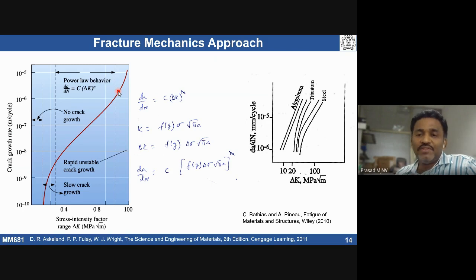People have established that a smooth surface finish, for example a diamond polish, can give improved fatigue performance compared to having only a rough oxide layer. After deoxidation you get some rough surface, and that is detrimental for fatigue. So the level of roughness can influence the fatigue behavior of a material.